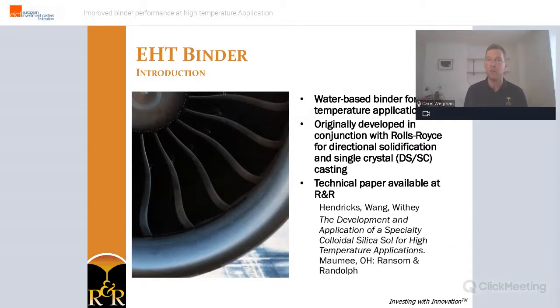Shells are put in conditions of 1500 degrees C for sometimes longer than 2 hours while under load of the molten metal. This requires the shell to possess adequate high temperature strength and creep resistance at levels that are much more demanding than those normally required in commercial foundries.